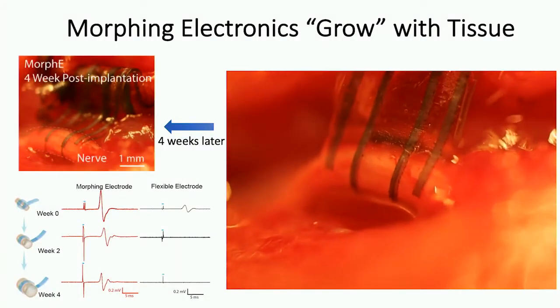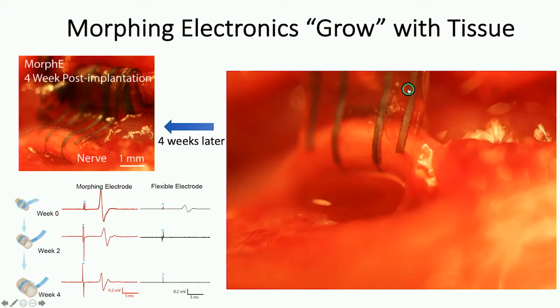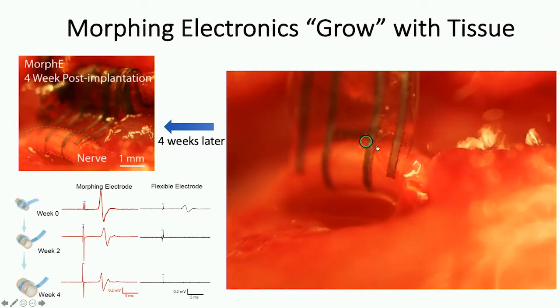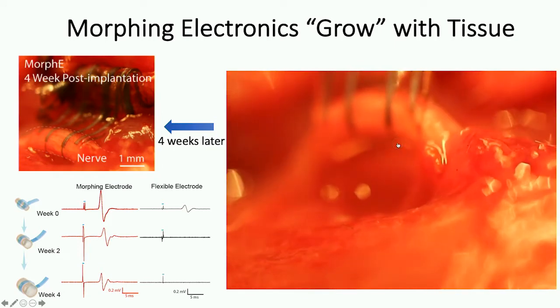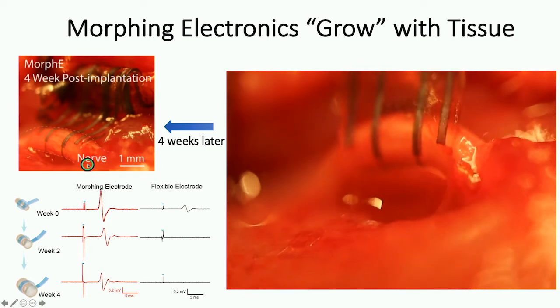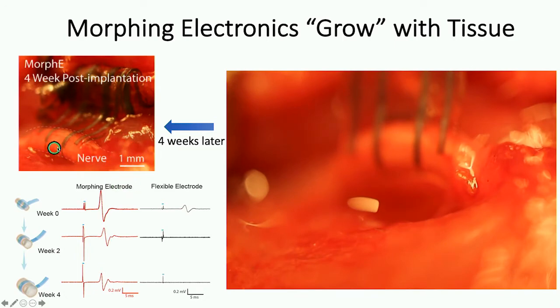So this is a nerve cuff that we put onto the nerve and then wrap around with the self-healing chemistry so that it can intimately wrap around the nerve. And then even after 4 weeks of implant, it still maintains intact without any damage, and we are still able to pick up the electrical signal that we use to stimulate the nerve. So this is an example of basically a material that we try to develop along the line of skin-inspired electronics, and then some kind of side spin-off applications from these materials.